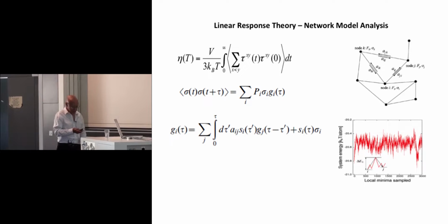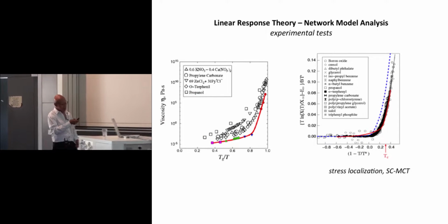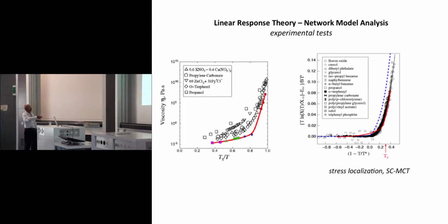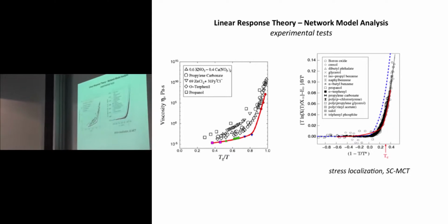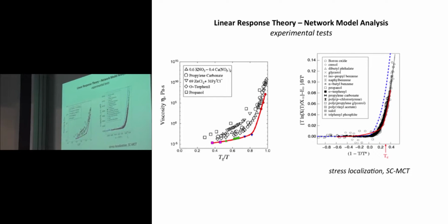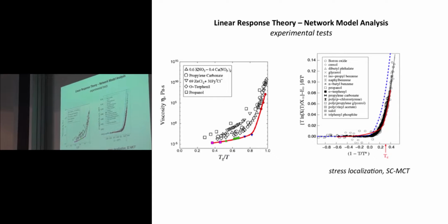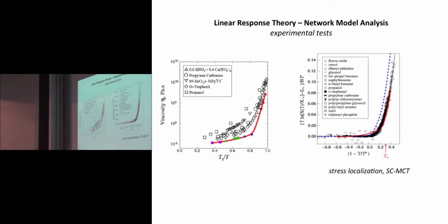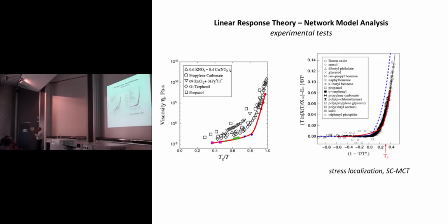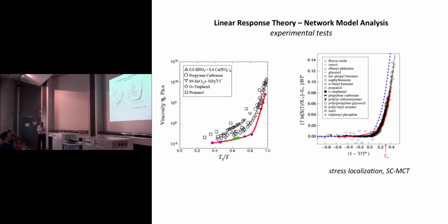And actually, we can solve this equation sort of analytically and reduce this calculation to a numerical calculation. The numerical calculation gives us results like this. By the way, to get this curve, you actually have to break the temperature range into 4 different parts, because there's a lot of change in the details that you cannot possibly hope to capture everything with one sampling. So you take the energy range of interest, you sample in 4 different regions, and then you calculate using the same approach with different inputs, and then you connect them. But nonetheless, you get something that's pretty good.